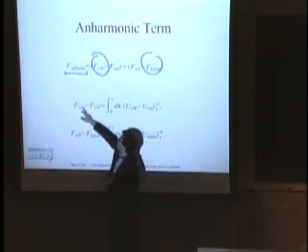And so we can actually break down this term in two parts. One that has to do with the difference between the harmonic crystal and our reference system, and one that has to do with the difference between our overall energy term here, or the overall free energy term, including nonlinear effects, minus the reference system.